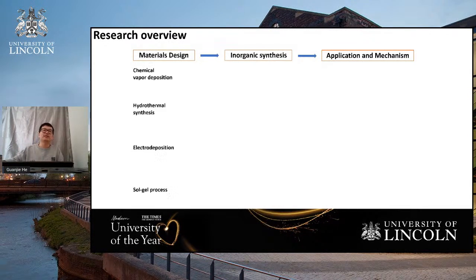And I use wet chemistry methods like hydrothermal synthesis, electrodeposition, the sol-gel method, and also thin film fabrication techniques like chemical vapor deposition to deposit the materials directly on the current collectors. So what does this process mean? That means we can form self-standing electrodes.